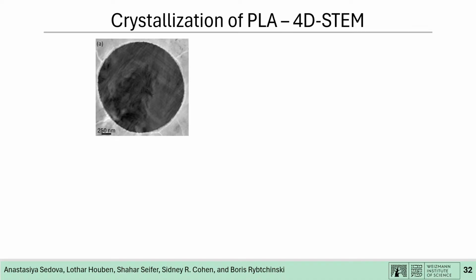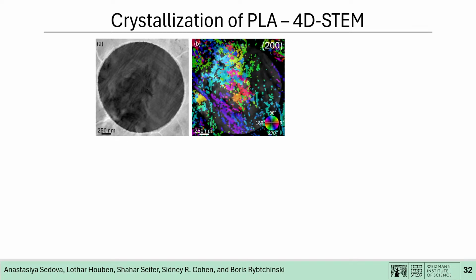We were working with polymers. We wanted to study crystallization of polymers by this technique. We started with PLA. This is a dark field STEM image. You can see some curvatures. Those are crystals of polymers. They are called lamellae. By computational means, we can obtain these orientation maps. Orientation maps are basically a vectorization of the diffraction planes. We can know the orientation of the crystals. The color wheel indicates the azimuthal angle.